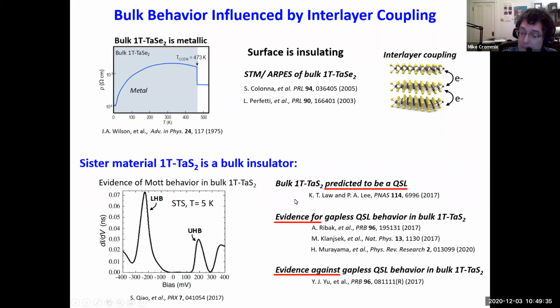And this material has been predicted to be a quantum spin liquid by Patrick Lee and coworkers. In fact, over the last few years, there has been some evidence for gapless quantum spin liquid behavior in this material, but there's also been some evidence against it. So there's some controversy here. And once again, in my opinion, the problem is the interlayer coupling of the bulk material that really complicates things. So an obvious thing to do is to get rid of the interlayer coupling by going to the single layer limit. And that's what we did.